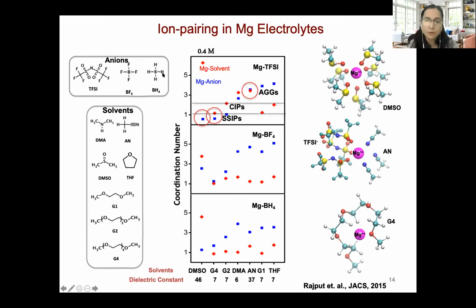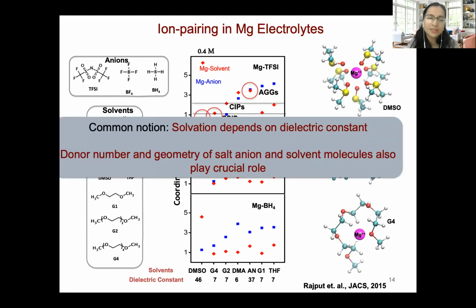Okay, lots going on here, but the take-home message from these results is that solvation is a very complicated phenomenon, and unlike the common notion that it depends only on the dielectric constant, it also depends on other factors such as donor number and the geometry of the anions and solvent molecules.